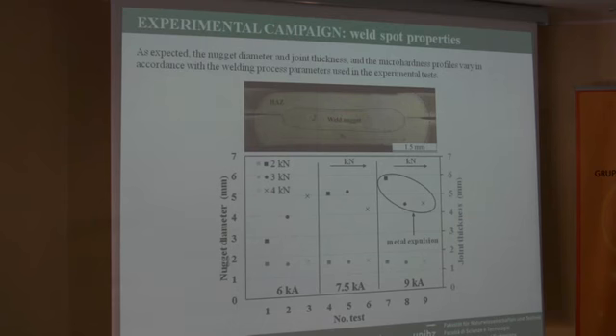In particular, you can denote that in the last tests we had some metal expulsions from the weld nuggets. That means that some metal goes away from the nugget, and so we can have problems related to the presence of defects in some cases, or to a reduction of mechanical strength. But particularly we can see that increasing the welding current, we have an obvious increase of the nugget diameter. However, here we do not have a defined trend because we have a weld metal expulsion. Instead, the joint thickness more or less does not change significantly in all the tests.